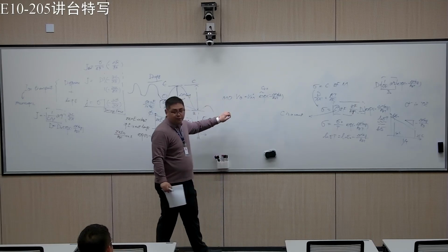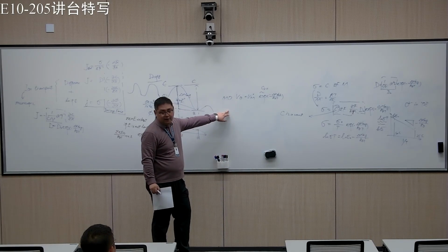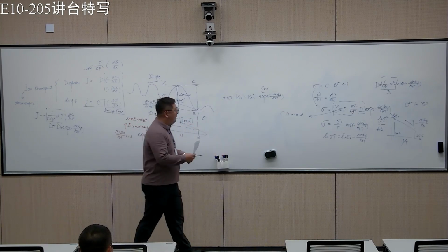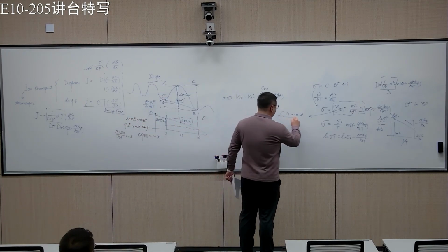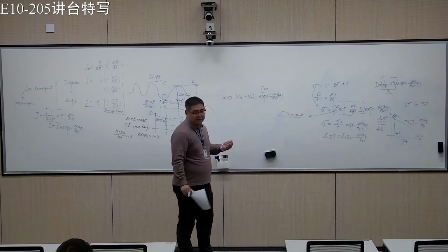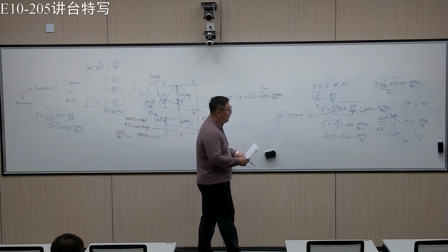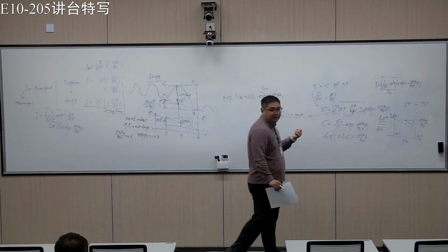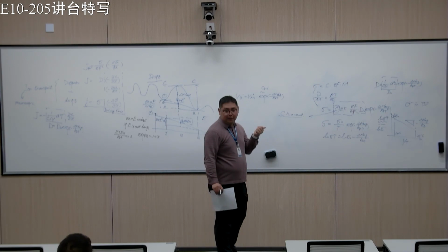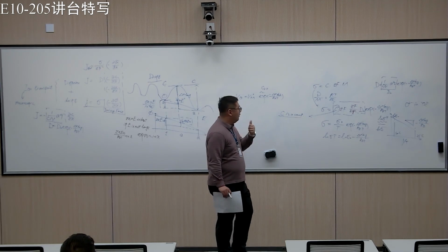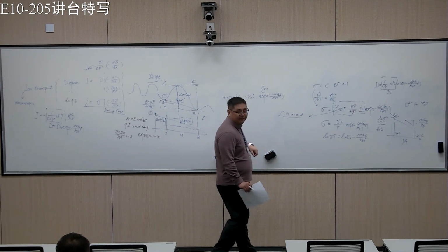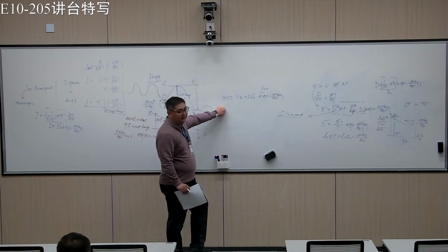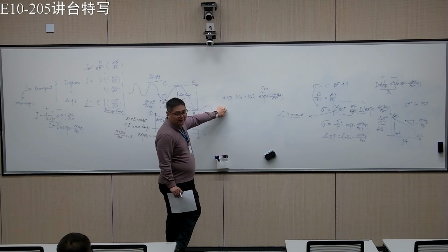If you form the intrinsic point defect, then in this case the concentration is not a constant. If you plot like this, what you get is both the migration barrier and also the formation energy for the defects. So this is the case often seen in halide perovskite.